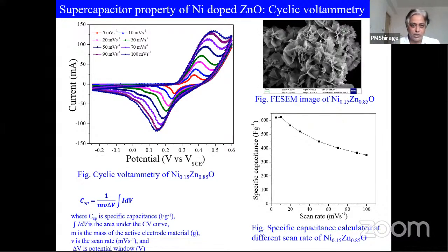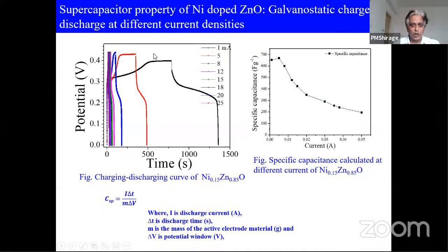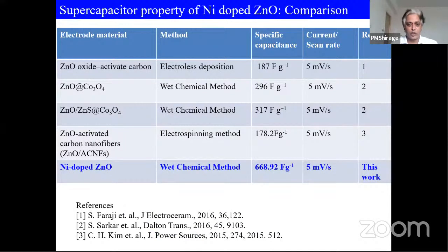Then another technique to estimate the specific capacitance is charging discharging. Basically, we charge the battery and discharge the battery, and by using that cycle, we can estimate the specific capacitance of the material. I utilized this discharging time to estimate the specific capacitance, and this also shows a specific capacitance of more than 650 Farad per gram. So our earlier cyclic voltammetry and charging discharging results are matching, and if you compare with the earlier reported data, our material is showing very high specific capacitance, almost 3 to 4 times higher than the earlier reported. It means that nickel doped zinc oxide is very good for supercapacitor applications.